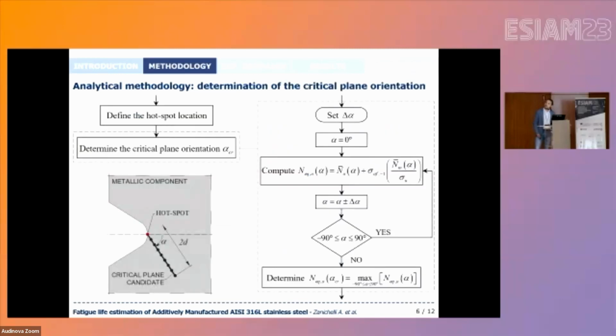So relatively to the determination of the critical plane orientation, once the hotspot is defined on the material surface, different material planes are considered, and these material planes pass through the hotspot and are characterized by an orientation alpha. So firstly, a proper angular increment delta alpha needs to be set, and then an initial value of alpha equal to 0 is assumed, that is, an initial critical plane candidate is considered. In particular, this critical plane candidate is represented by a segment which starts at the hotspot and moves inward to the structural component up to a length equal to twice d.